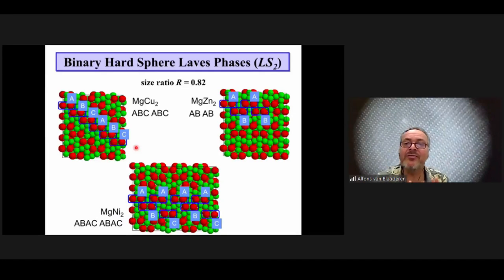Why it's optically very interesting is because the big spheres form, if you burn away the smaller spheres, for instance, they form a diamond lattice. And a diamond lattice is for photonic crystals very, very interesting. So conversely, if you burn away the big spheres and the small spheres are there, then it's also very interesting because that's called a pyrochlore lattice, and that also has a band gap for relatively low contrast. However, for bulk crystals, you don't get the magnesium copper 2 interesting phase, but you get the magnesium zinc 2 phase, which unfortunately is optically not interesting.